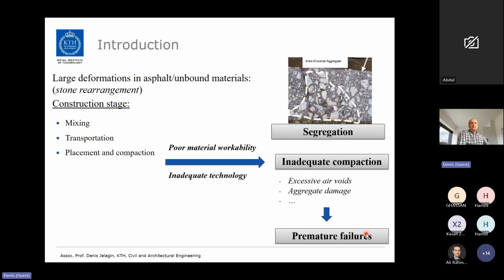And as we all probably know, inadequate performance of material during those large deformation situations may lead to problems in the field. Inadequate material workability or inadequate technology used for a given material may result in mixture segregation. It may result in inadequate compaction, excessive or too little air voids, aggregate damage, and so on. And those things are known to be one of the primary contributors to premature failures in the material.